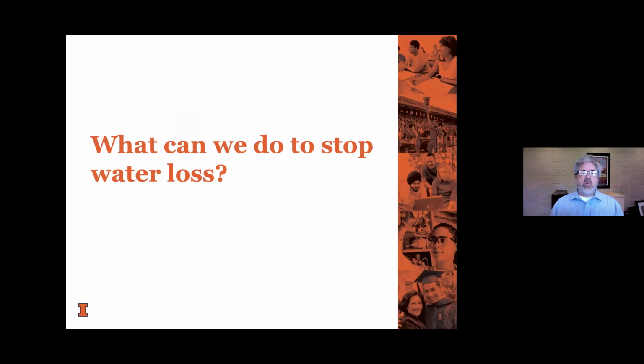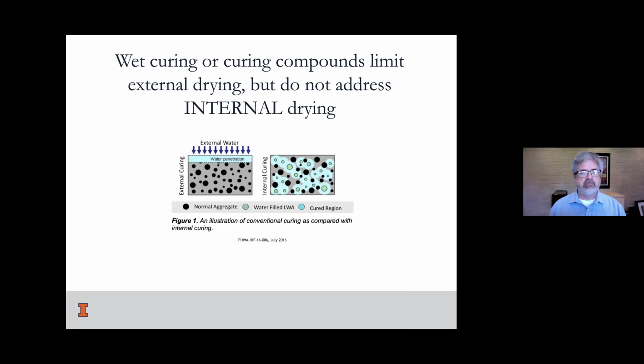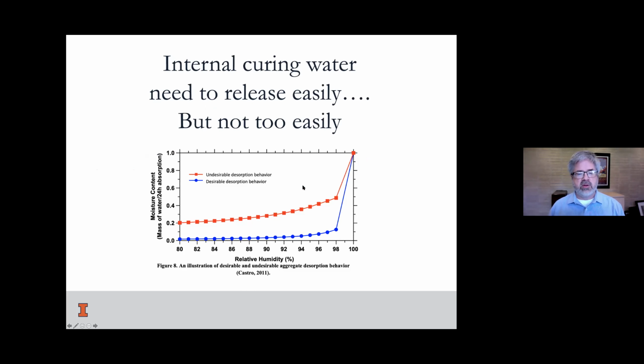So we want to try to stop that water loss if we can. How are we going to do it? Well, we certainly go through wet curing or conventional curing to keep water leaving from the external surface. But we also have this problem that would be true even if the material was perfectly sealed. This problem is not due to external drying shrinkage. And so we have this idea of internal shrinkage.